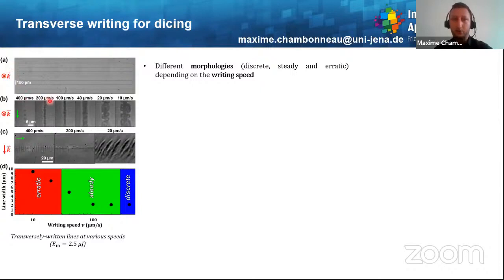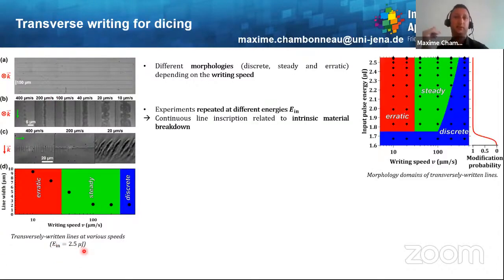And the line morphology can be discrete, steady, or erratic, mainly depending on the writing speed. So here, the input pulse energy is constant at 2.5 microjoule. And we repeated this kind of experiment at different input pulse energies. So here is the input pulse energy on this axis, the writing speed, the black points represent some tested configurations, which allow us to discriminate different domains for the line morphology.